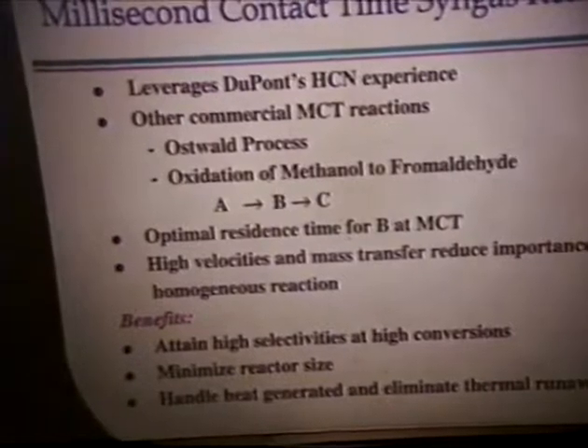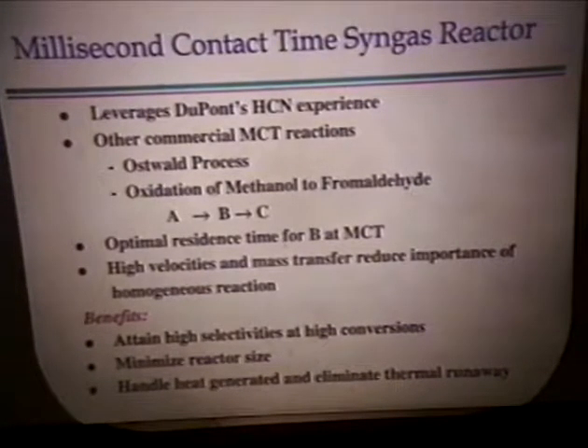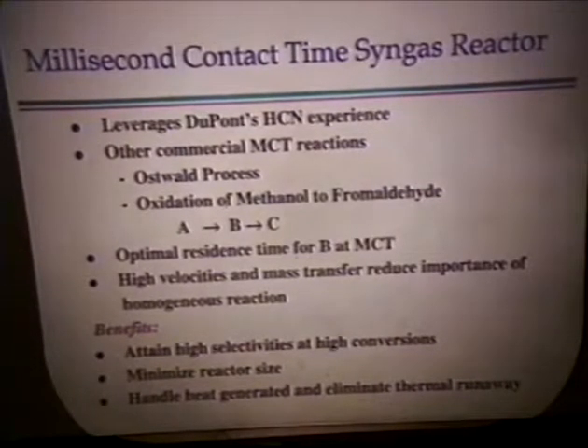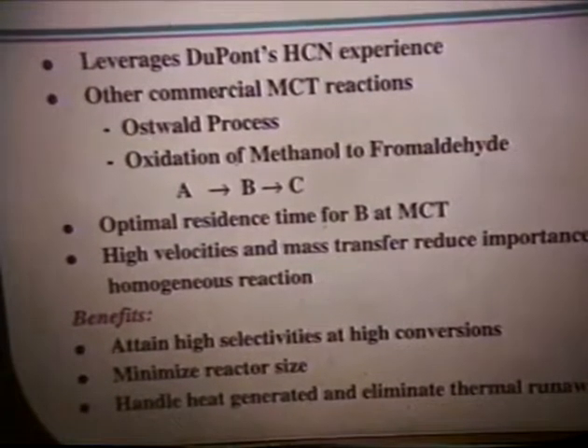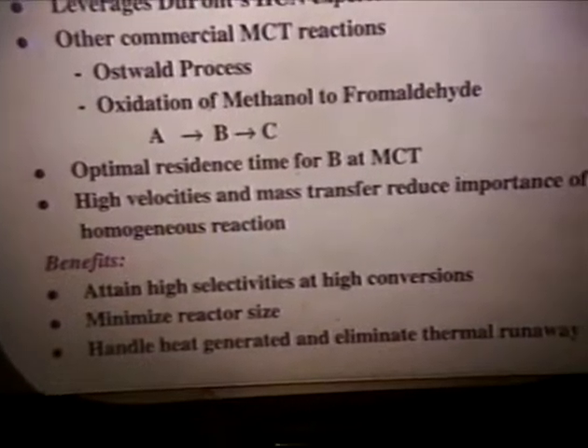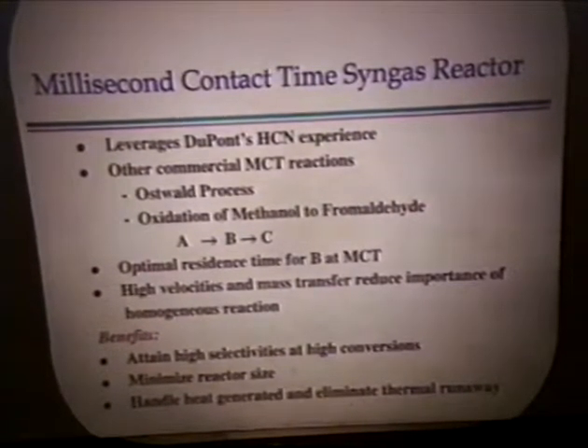Historically, DuPont has had a long record of doing millisecond contact time catalysis with their HCN technology using a platinum rhodium catalyst, so they're very skilled in this area. Another well-known process is making nitric acid, the Ostwald process, and making formaldehyde from methanol. All of these are short contact time commercial entities. The trick here is that you control your kinetics so that you stop at product B without undergoing secondary reactions to the undesirable product C.